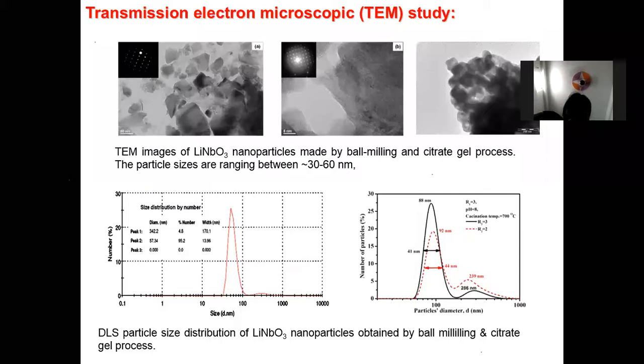And then you see the DLS, dynamic light scattering, program in the machine to see where this size falls, because it is basically a range. It will not be of a single size. Say in this case it is 30 to 60 nanometers, which is enough for the second harmonic generation application. The size should be less than 100 nanometers. So it is coming about 30 to 60 nanometers.